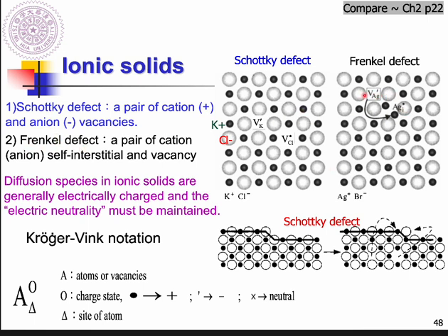Actually, also a pair, but it's due to one of the ions, either silver or bromide, moving to the self-interstitial site. So you can visualize a pair of a vacancy left behind and the corresponding ion. You can see the silver was here at the self-interstitial site, and what is left is the corresponding vacancy, and you also have one negative and one positive, which also reaches electrical neutrality.